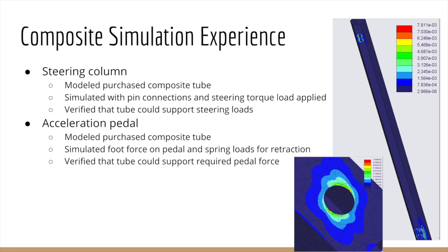Both of the images on the right show strain across the components. The strain is the failure method for composite components, as the strain must remain under 0.017 in the components. So I analyzed that and could see that the max strain of the part on the right, the steering column, is 7.811 times 10 to the negative third, which is much under the 0.017, therefore this component passes, and that's how I was able to analyze the results that I was getting.